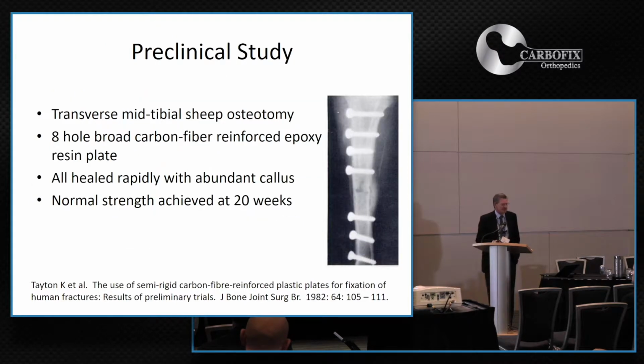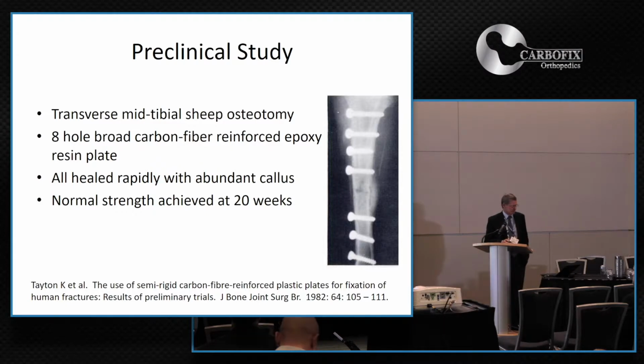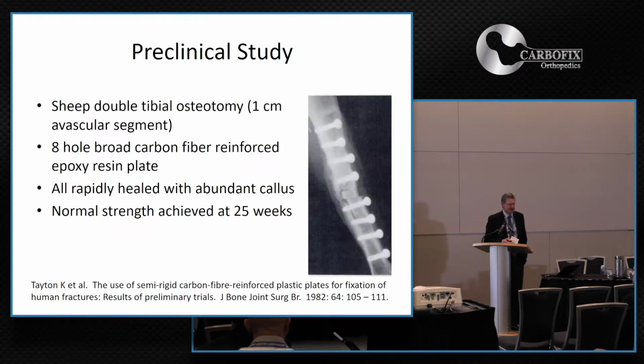And they reported first on a preclinical study. This was a transverse mid-tibial sheep model fixed with a plate. All of these fractures healed with abundant callus, and normal strength was achieved comparable to the contralateral side at 20 weeks. They also did another one in which they had a double osteotomy, so they removed a centimeter of bone, so it was devascularized. And again, all of these went on to heal, normal strength to the contralateral side achieved by 25 weeks.